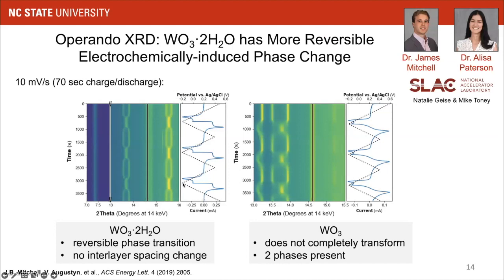These are the electrochemical input. This is the current response. You can see that at the redox peaks, there's this very distinct transition of the hydrate into a new crystal phase. There's no interlayer spacing change, however. So that idea that protons could be moving along these pathways is not really supported by the X-ray diffraction. What we can say is that we're not seeing tungsten-oxygen bond distances change along that interlayer axis.